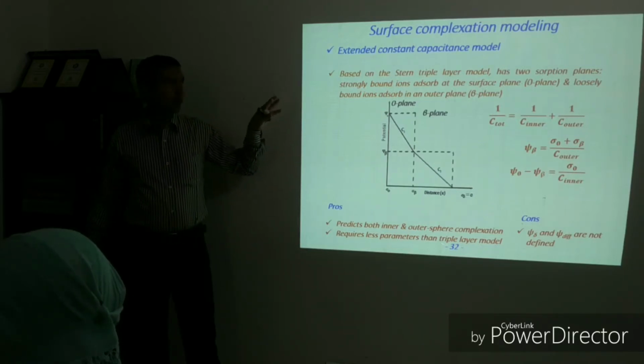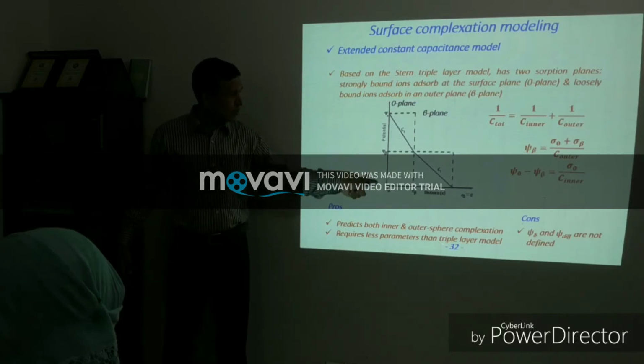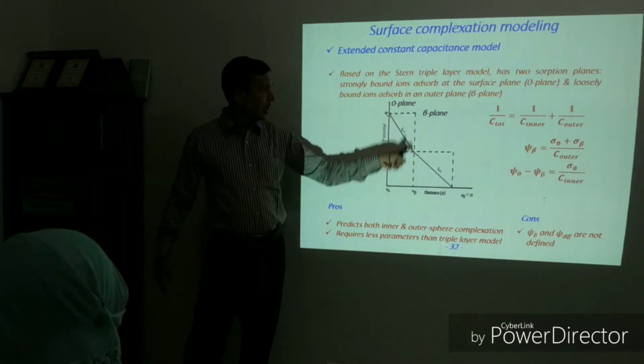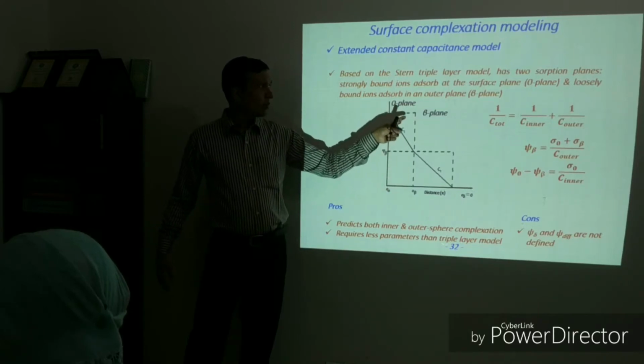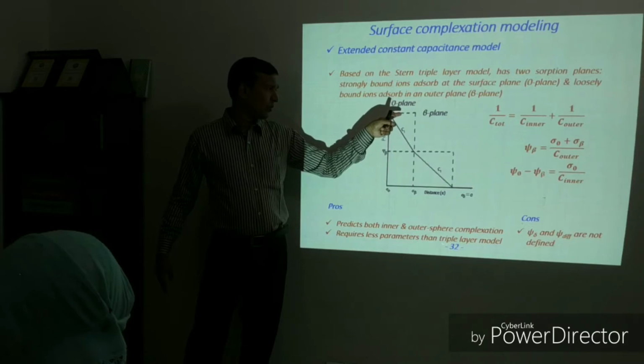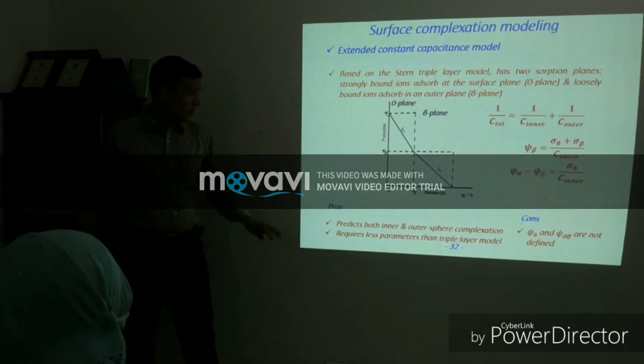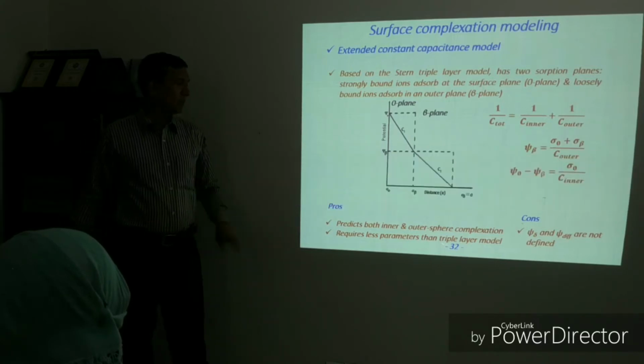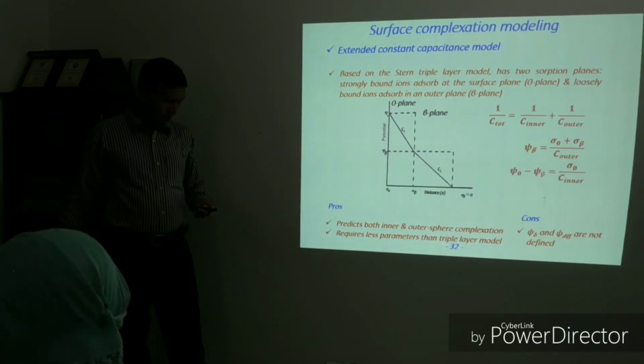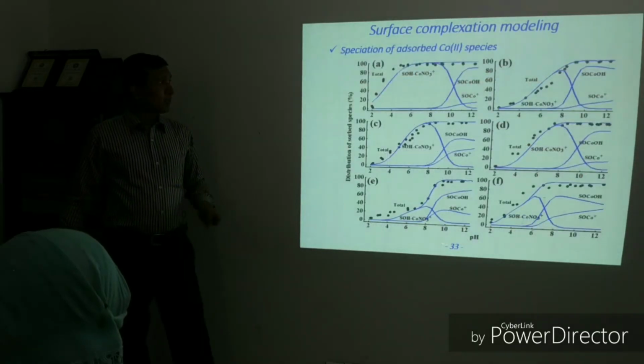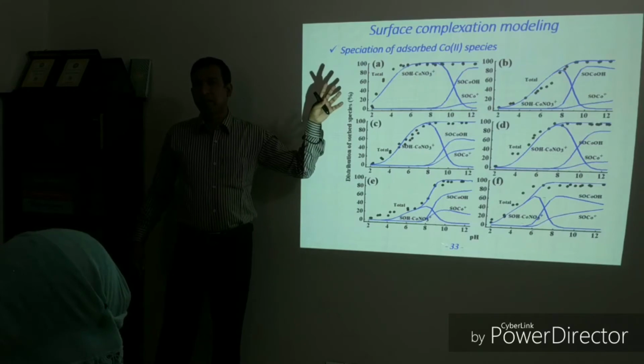It has two sorption layers. The first one is the zero plane or surface plane, where strongly bound ions are adsorbed, and the second one is the beta plane, where weakly bound species are adsorbed. So why have we used this? Because it can predict both inner and outer sphere complexation and requires fewer parameters than triple layer models. And previously I have shown the surface complexation modeling fitting for adsorption of cobalt and other cases.